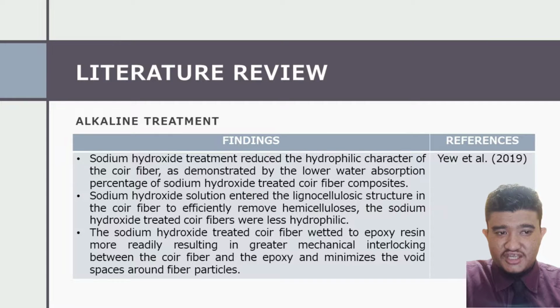Sodium hydroxide solution entered the lignocellulosic structure in the coir fiber to efficiently remove hemicellulose. Then the sodium hydroxide treated coir fiber were less hydrophilic. The sodium hydroxide treated coir fiber adhered to epoxy resin more readily, resulting in greater mechanical interlocking between the coir fiber and the epoxy and minimizing the void space around the fiber particle.